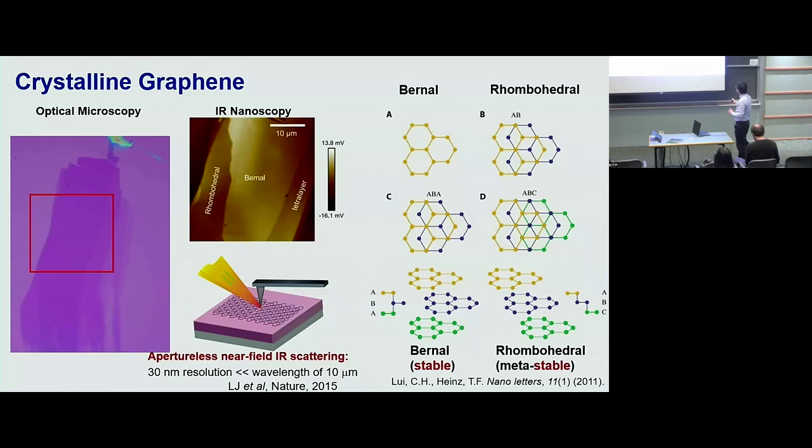It's called the rhombohedral stacking order, which is the so-called ABC, ABC, ABC stacking. That corresponds to when you stack layers on top of what's existing there, you keep shifting in the same direction, okay? And then you get the rhombohedral. So Bernal stacking is more stable than rhombohedral. Roughly 80% of graphite is Bernal.